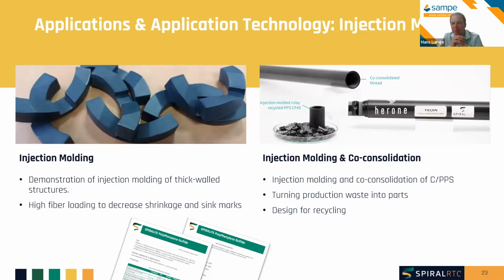Also an example, and that was performed by Heron, that's on the right side of the slide, is injection molding and co-consolidation. So what they did is they made this tube from continuous fiber reinforced materials, and used some of our recycled PPS with the 40% by weight fiber loading, made it an injection molding inlay, and co-consolidated with the bar. And that's really, you can turn production waste into parts. And it's also beneficial if you look at the design for recycling, since both the insert and the tube are of similar materials, so you can put this at the end of life in a shredder and reuse it again. So that's also, I think, one of the nice advantages here.